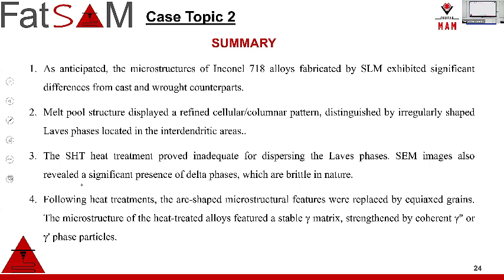But in contrast, we need to increase, because there is a ratio of titanium, aluminum plus carbon, increase titanium and niobium ratio, which provides very much segregation and formation of new intermetallics. And still, it's a welding procedure, joining of powder to powder. Carbon is one of the most active elements in the microstructure. Its activation energy is very low, so whatever you do, like just put it at mostly 120 Celsius, carbon will start to segregate.